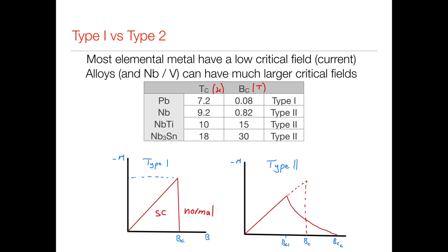What was found was that when we alloy the materials, we get a different type of behavior. Initially it starts off the same. As we increase the magnetic field this way, we get the perfect diamagnetism. But now at a slightly lower field, this changes, and the magnetization is less than what would be needed to cancel out the applied field.